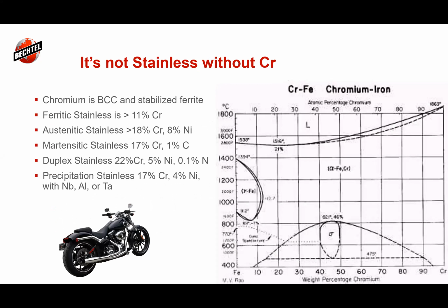Stainless, this is a little snippet of what I've got. Stainless is, as we move into that, it builds on some of the carbon steels. It's not stainless if it doesn't have chrome, so we have to have at least 12.5% chrome. And here's a chrome iron phase diagram. But we have ferritic stainless, austenitic stainlesses now have both chrome and they add nickel in, around at least 8% nickel. You have martensitic stainless that we'll see quite a bit in rolling mills and other sorts of high strength applications, the duplex and the precipitation strength.